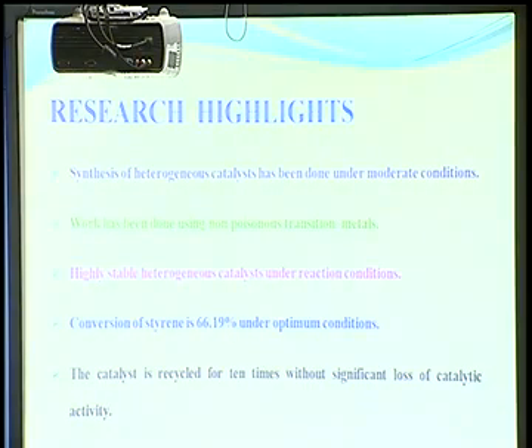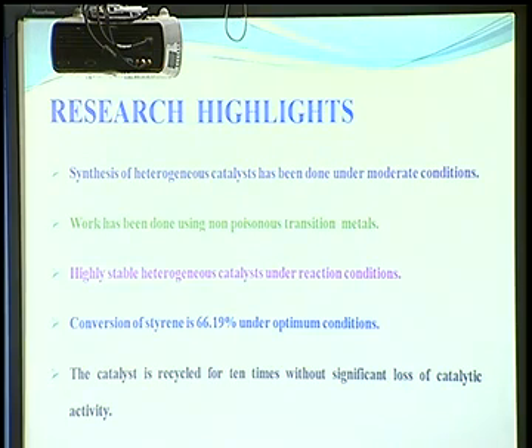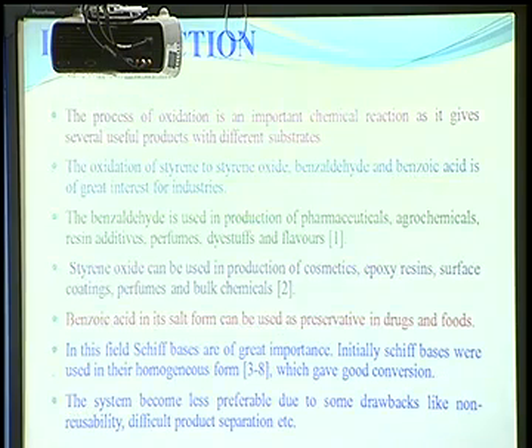Research highlights. The synthesis of my catalyst has been done under moderate conditions. Work has been done using a non-poisonous transition metal, that is copper, and a highly stable heterogeneous catalyst under my reaction condition. The conversion of styrene is 66.19% under optimized conditions, and my catalyst has been recycled 10 times without any significant loss of catalytic activity.